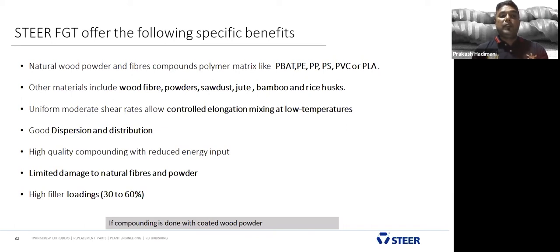Okay, and FGT technology also gives controlled elongation mixing and lower temperature, and gives good dispersion and distribution and high quality of the pellets, and also no degradation in the fiber. And it helps customers load 30 to 60% of wood powder.